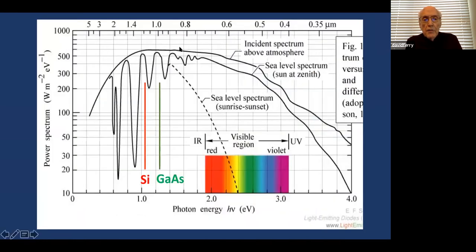Now, this is the spectrum. The top black curve is what the sun puts out, and what you will see if you're above the atmosphere in the space station looking at the sun. You get this nice black curve. It's a Bose-Einstein distribution at the sun's surface temperature of about 5,400 Kelvin. And it's relatively smooth. What gets to the surface of the Earth, though, that's this next black curve. That's at sea level with the sun directly overhead. You see a lot of absorption in the atmosphere, which eats up a lot of the photons that can come in. Silicon band gap is right here. This is photon energy. So photons on this side of the red line will be absorbed in silicon. On this side of the green line will be absorbed in gallium arsenide.